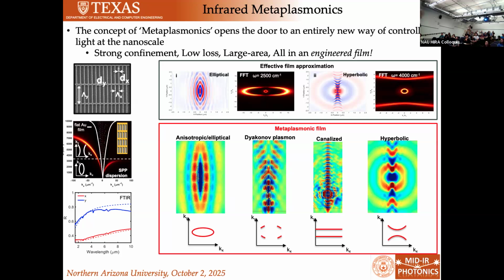You're also, there's a reactance there that you're messing with. And it turns out that depending on your dilution in different directions, you can actually engineer these metaplasmonic films to have different permittivities in different directions. So this is, for instance, the permittivity in the X direction, and this might be the permittivity in the Y direction. And this is, of course, what a flat metal film looks like. I should say, this is the dispersion of your surface plasmon mode in X and Y. This would be the dispersion in just a flat metal film.